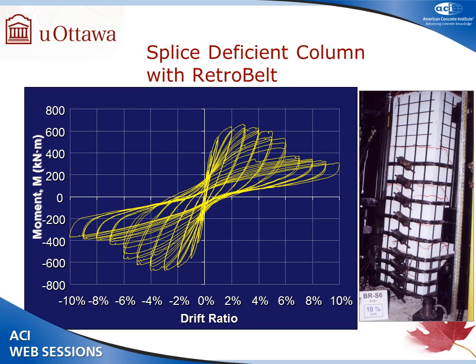And here is a square column with 20 times bar diameter splicing in the potential plastic hinge region, and hence it did start slipping after 1% drift, whereas when we applied this time, we had to go up to 50% of Fy in terms of level of prestressing. Then it performed fairly well, and once again we reached 4% drift.